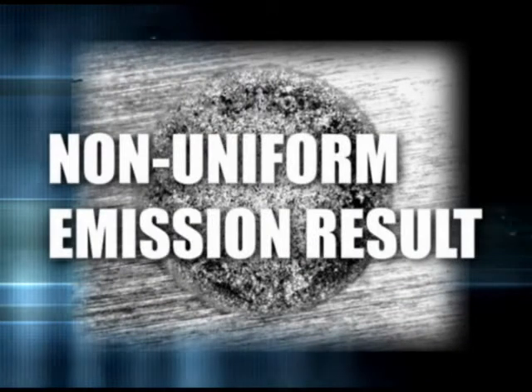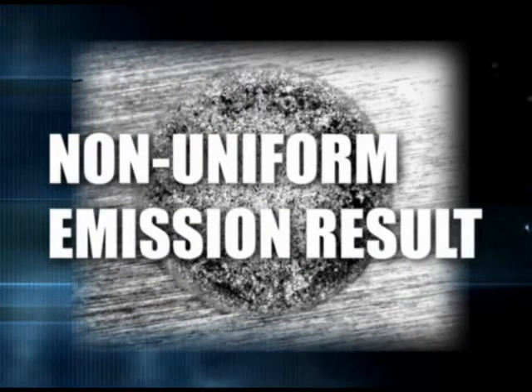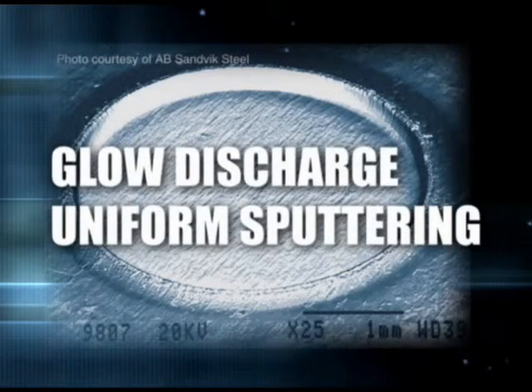Glow discharge sputtering provides a controlled, consistent emission where sample homogeneity and other artifacts do not affect the emission, unlike other methods of excitation where excitation is strongly dependent on sample homogeneity.